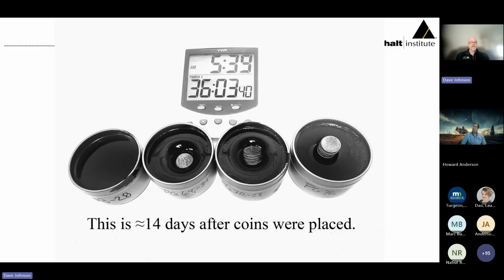But the dimes in the 58-28 on the far left have been completely swallowed up. The 64-34 and the 70-28, we can still see those dimes, but they've made notable penetration into the binder. And then finally the 76-34, while yes, there was a little bit of a distortion, it's quite minimal.